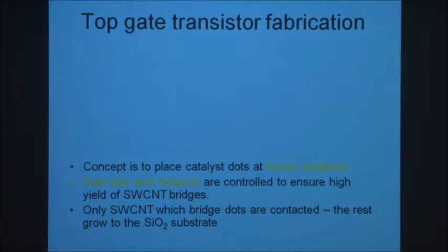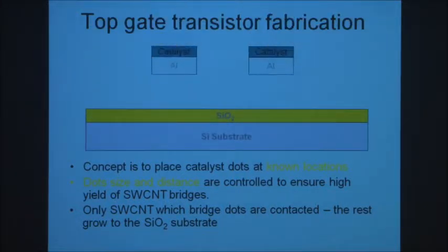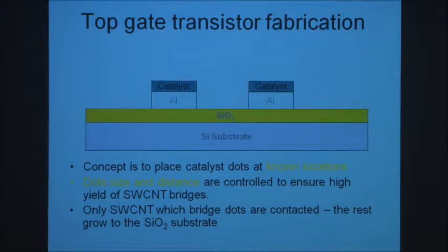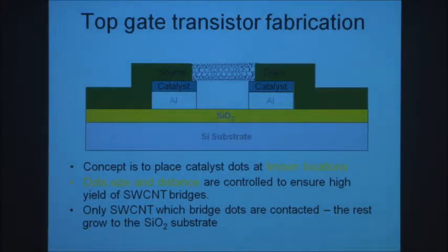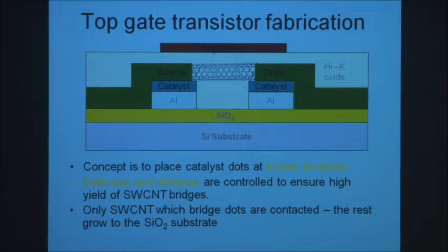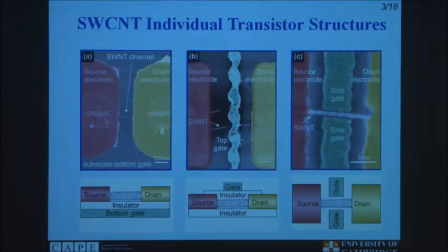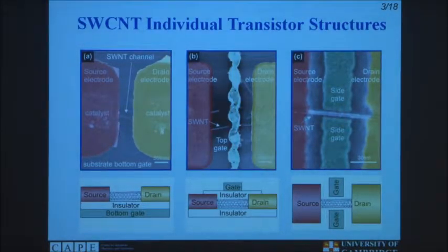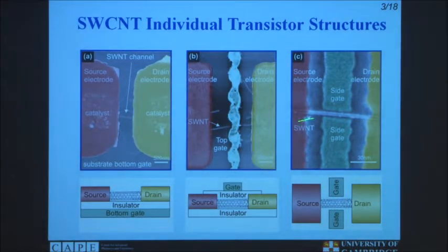You can also do top gate, exactly the same principle. You put a bottom substrate, catalyst, grow the nanotube, source and drain, put on the top gate, high K dielectric for instance, and you've got a top gate transistor. You can make side gate transistors as well. It's all feasible, and here's some stuff we've done. So this is your bottom gate, your side gate, and a top gate. They all work, and they give you reasonably good transistor characteristics, but it really takes a lot of time and effort to do that.